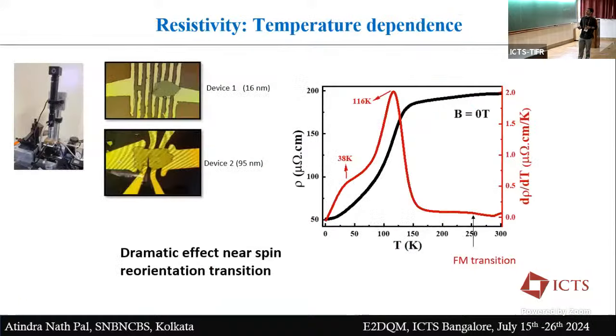Okay, but doing transport is not easy in this material, because these ferromagnetic 2D materials can often oxidize, and we have to make a good contact. So the strategy we have taken is that we have a transfer setup, and using the transfer setup, first we make the electrical contacts. These can oxidize, but what we did is we made the device, and within half an hour, using PDMS, we put the flake on top of this contact, and immediately we coat PMMA. Then we check the electrical transport, and we found that it can give a very nice contact.